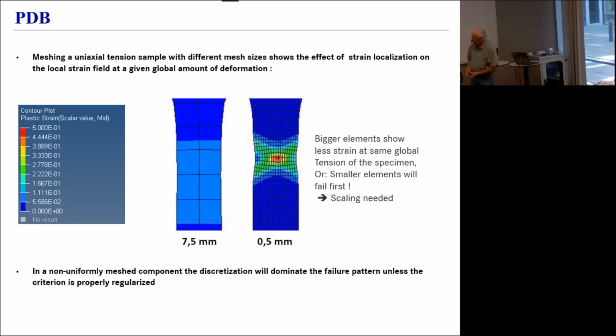Now, this is the reason that we absolutely need regularization when we do applications, because your mesh in a real-life model is never homogeneous. You always have a mixture of small elements and larger elements. And if you have no regularization, the failure pattern will actually be dominated by the local element size rather than by the physics.